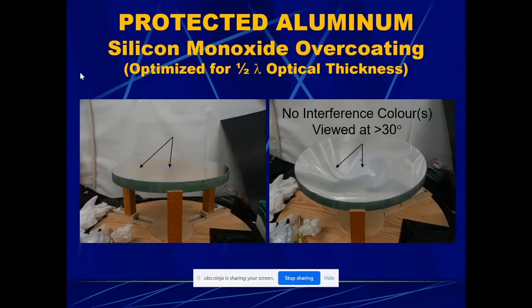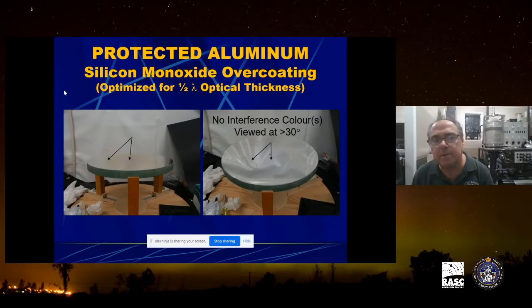So when we're putting on the magnesium fluoride, okay, we'll see it go from a yellow to a magenta over a few minutes, and then we stop it around a magenta color, and then we introduce the cerium dioxide, and the cerium dioxide will then change the color from magenta to green, and then the green will slightly go away. And this is face on. But when you look at it on an angle, you'll see these interference colors.